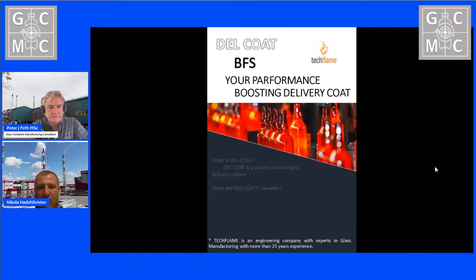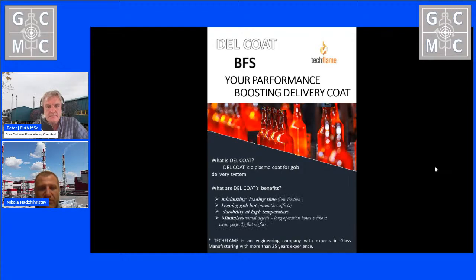It was all about Del Coat and what kind of benefits you can have: minimizing loading time, low friction, keeping the gob hot. Its durability at high temperature is well known because the material is very stable. Its temperature resistance is up to 1,200 degrees, and lastly, the coat minimizes visual defects, gives long operation hours without wear, and the surface is perfectly flat. The gob doesn't move during the transportation.